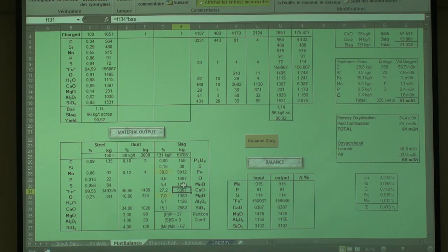Then we come to the MnO. MnO is, as you see, the quantity times the weight of slag. So, in fact, I have to jump to the slag weight. We are able to calculate the SiO2, Al2O3 and CaO this way. But to calculate the total amount of slag, we have to make a trick, because the other weights we don't know, because it depends on an equilibrium.